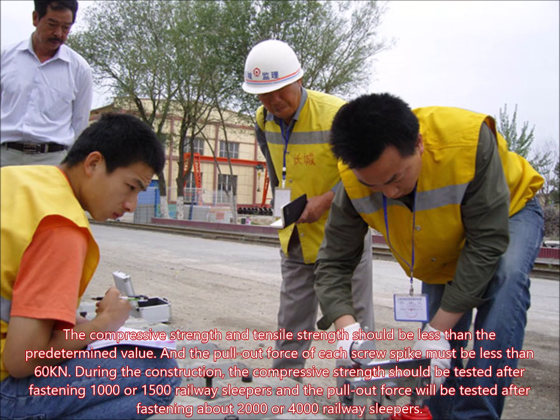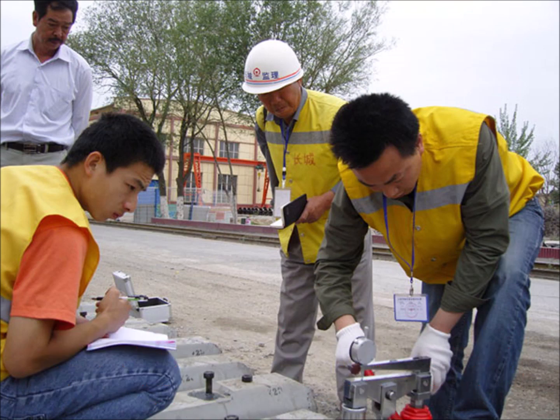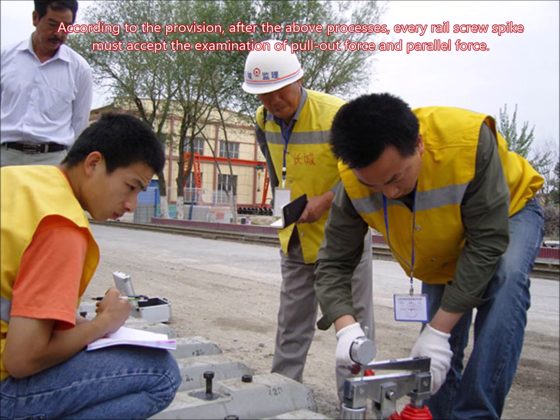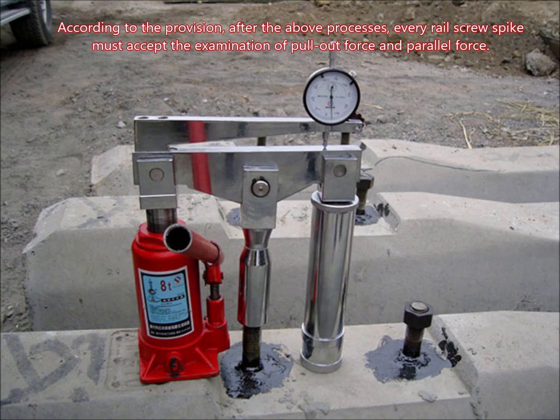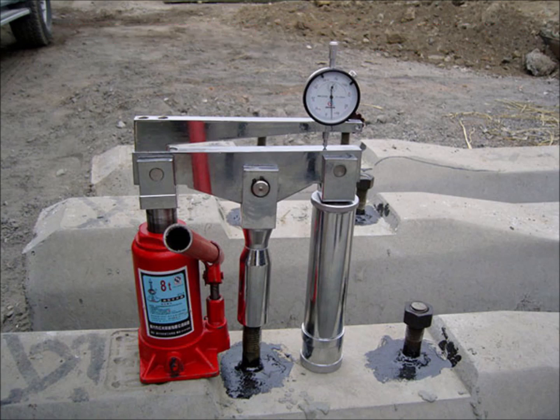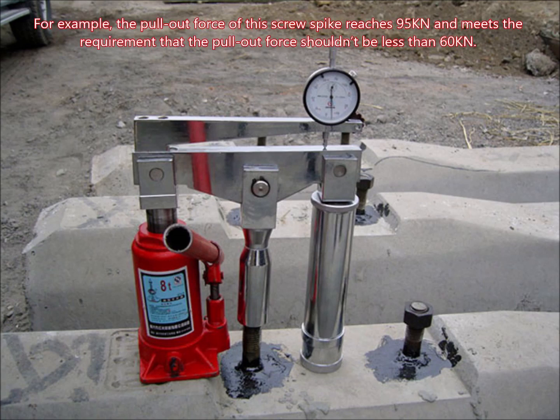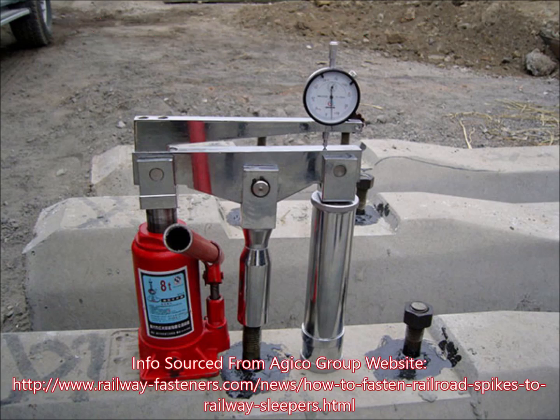During the construction, the compressive strength should be tested after fastening 1,000 or 1,500 railway sleepers, and the pull-out force will be tested after fastening about 2,000 or 4,000 railway sleepers. According to the provision, after the above processes, every rail screw spike must accept the examination of pull-out force and parallel force. For example, the pull-out force of this screw spike reaches 95 kN and meets the requirement that the pull-out force shouldn't be less than 60 kN.